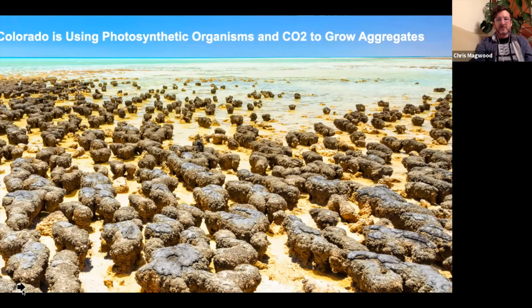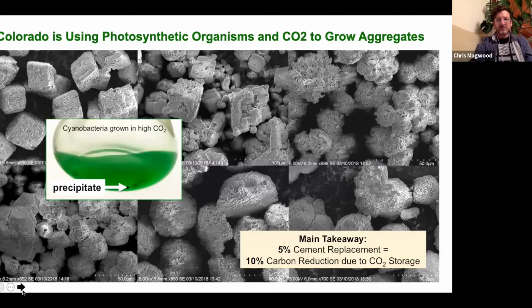If you go to the next slide, Chris, what I wanted to show is that in my lab, we're growing tiny little stromatolites. We're growing tiny little limestone particles using these bacteria. So this is a flask here, a green flask of these photosynthetic organisms. Using artificial seawater, we're able to get the bacteria to use CO2, nucleate a limestone crystal, and in effect grow limestone that we could then use as a filler or as an aggregate replacement in Portland cement concrete.